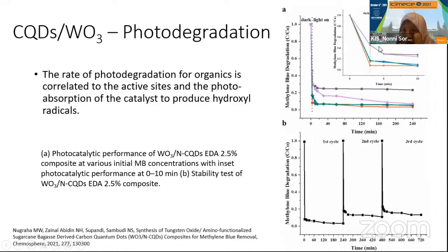So we also tested the material to degrade the same methylene blue, but we increased the concentration up to 50 ppm. Even until 50 ppm, we still can get around 70% degradation. Okay, and then after that, we tried to recycle the material. But we only did until 3 recycle tests. Until 3 recycle tests, we can keep the performance of the material to be more than 80%. So we still can remove 80% of the methylene blue from the solution, even if we reuse the material until 3 times.